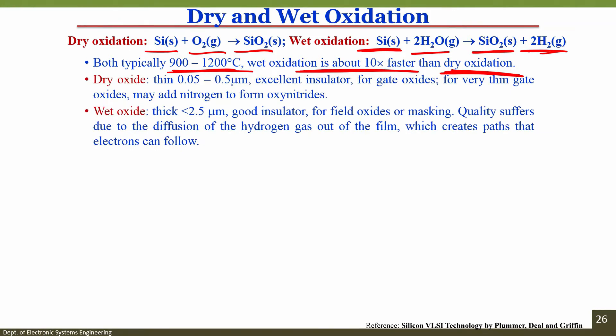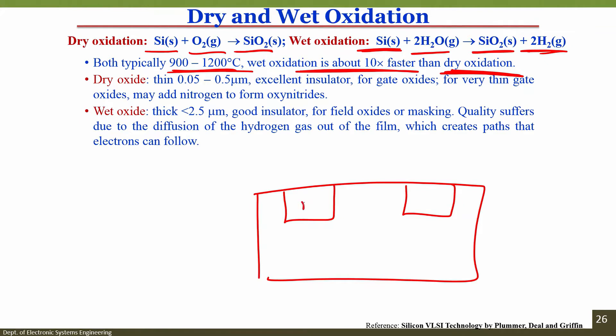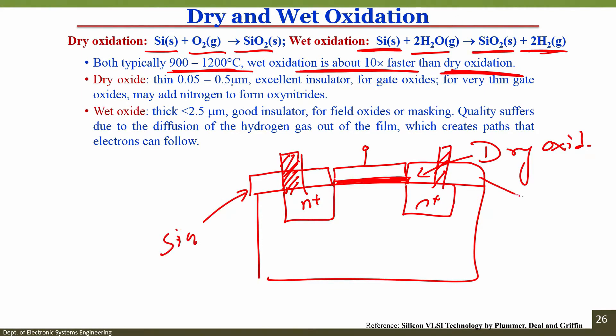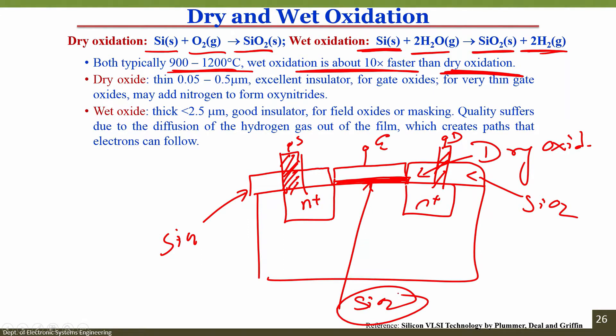Dry oxidation has the limitation that you can only grow a thin layer of oxide, about 0.05 to 0.5 microns. However, it is an excellent insulator. For the gate oxide in a MOSFET — a transistor with N+ regions and a gate layer — this thin gate oxide layer is grown using the dry oxidation process. The oxide protects the device everywhere, and windows are opened in the silicon dioxide using photolithography to access the source and drain contacts.